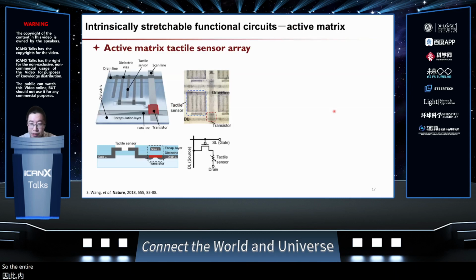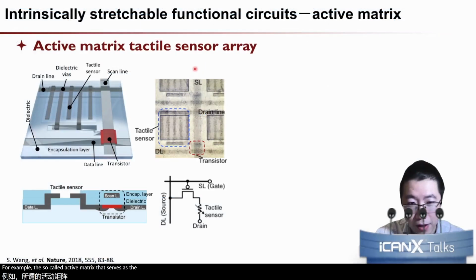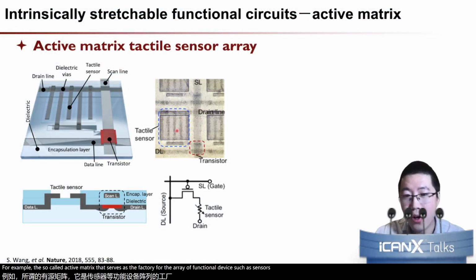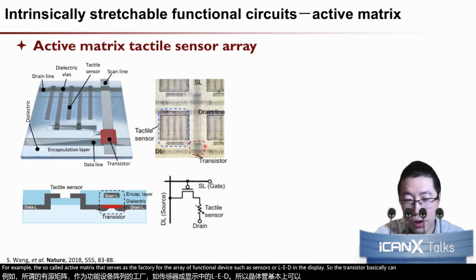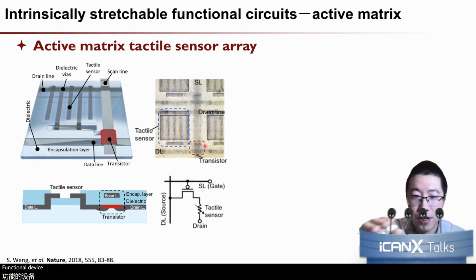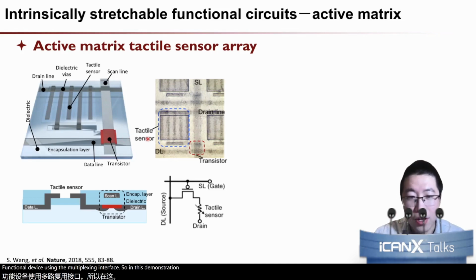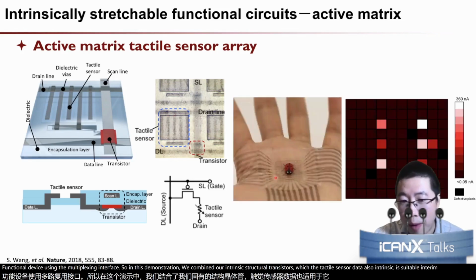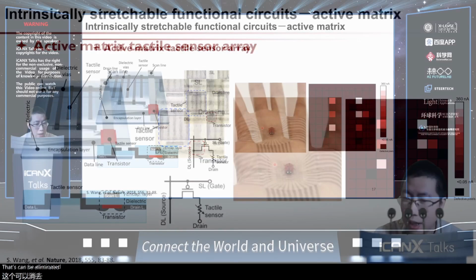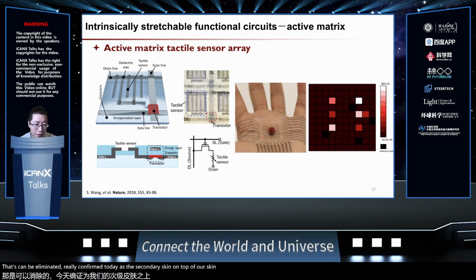So, enabled by this, we took another step by integrating the transistors in the array into functional units. For example, the so-called active matrix that serves as the backplane for an array of functional devices, such as sensors or LEDs in a display. The transistor can control the on-off of each individual functional device through multiplexing. In this demonstration, we combined our intrinsically stretchable transistors with a tactile sensor that is also intrinsically stretchable into a 10 by 10, 100-pixel array that can be laminated conformably as a secondary skin on top of our skin, for example on the palm of the hand, to serve as the interface for mapping physical contact by reading the current level from each of these individual pixels.